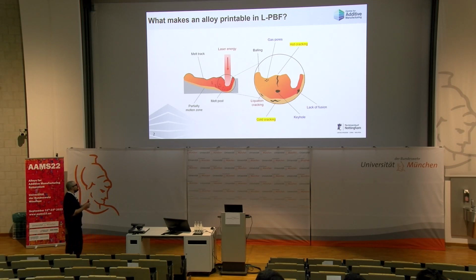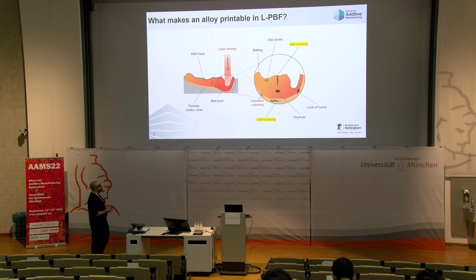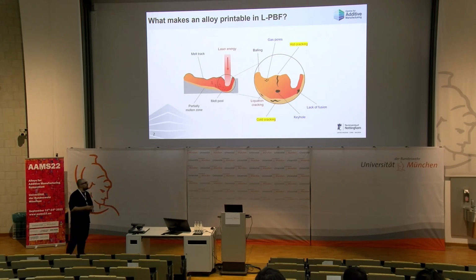When we talk about porosity, of course, we have gas pores, lack of fusion, and keyholes, and all these types of porosity, we know roughly the trend of that as a function of process parameters. But when we're talking about cracking, especially hot cracking, which is quite detrimental in aluminium alloys, we don't know how it is controlled in the L-PBF process. We have some hints, some idea, but actually we don't know how cracks change as a function of process parameters.